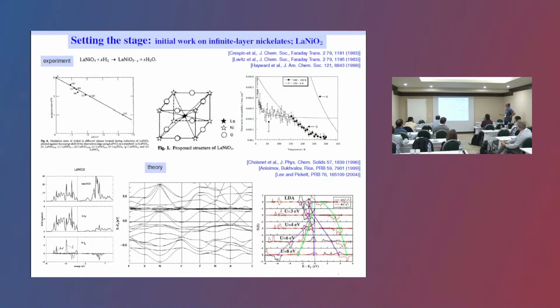Okay, but then of course there was a lot of work, as I said, historically on these infinite layer compounds, because this has the cuprate-like structure. You pull out oxygen and they form this nickel 1+ state. Indeed, that was looked for, but we heard already that the magnetic behavior is quite different from the cuprate, so there's not a nice antiferromagnetic ground state, at least at stoichiometry, that's what people think, and it's still not found.